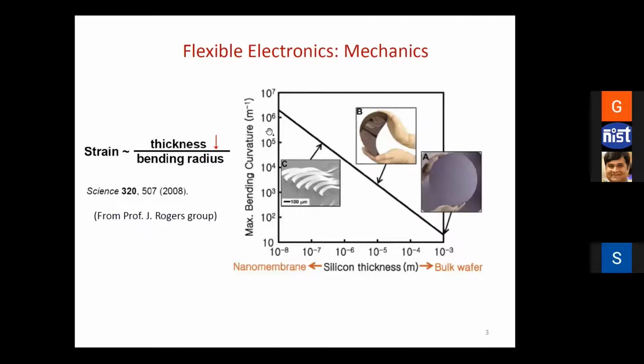Because of this, if you see this plot over here, one extreme is a bulk silicon wafer, which has a thickness of around 10 to the power minus 3 meter, that is roughly 1 millimeter. On the other extreme is a nanomembrane, which is around 10 nanometer thickness. This silicon wafer, if you reduce its thickness, will start getting flexible. The same wafer which is brittle will start becoming flexible. And if you continue reducing its thickness down to nanometer regions, where you convert it into a silicon nanomembrane, it has a very high bending curvature, right? So this plot basically talks about bending curvature versus thickness. With higher thickness, you have less bending curvature. With lower thickness, you have more bending curvature. So thickness plays an important role in bending things and getting higher bending curvatures.